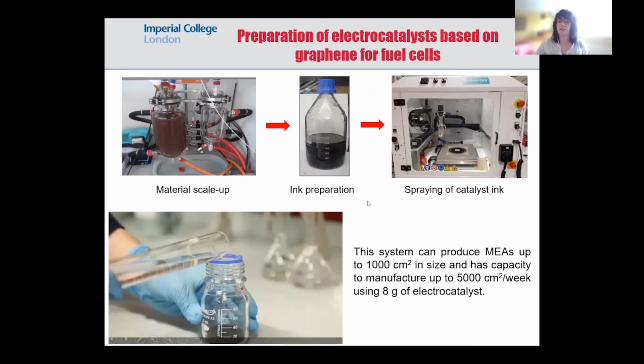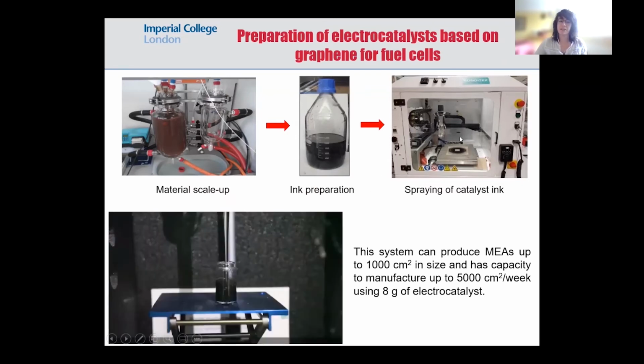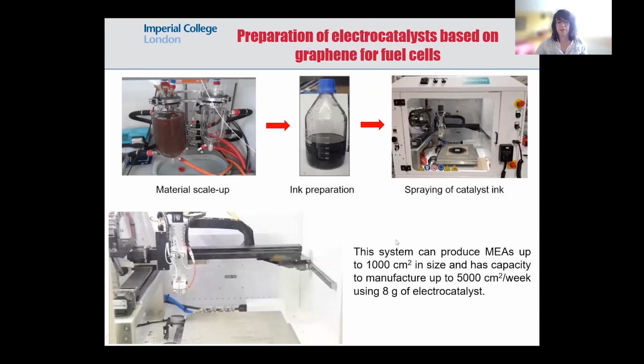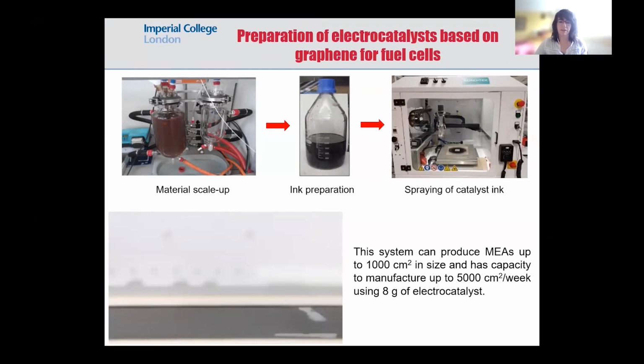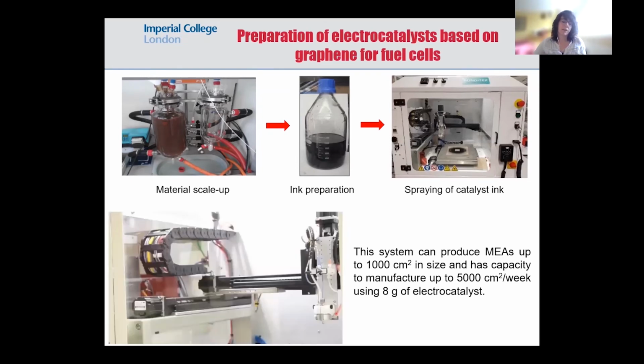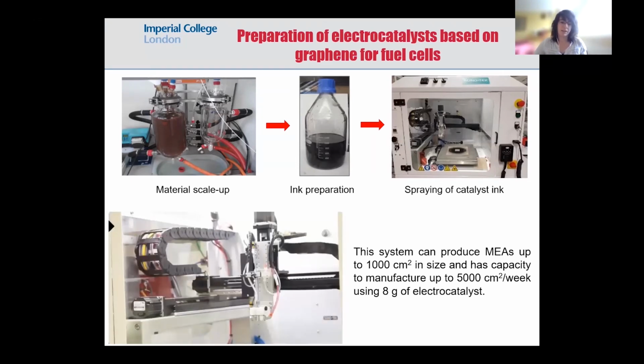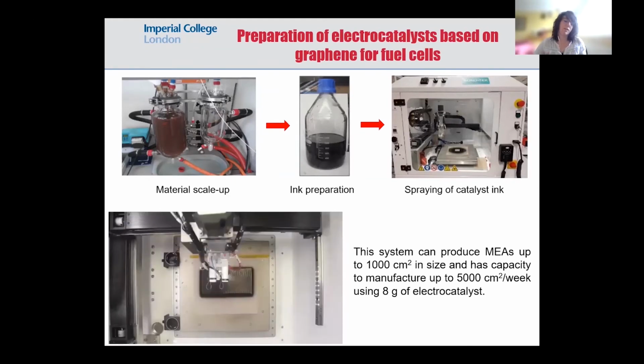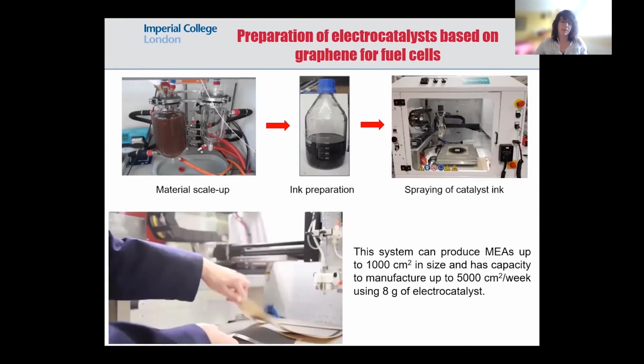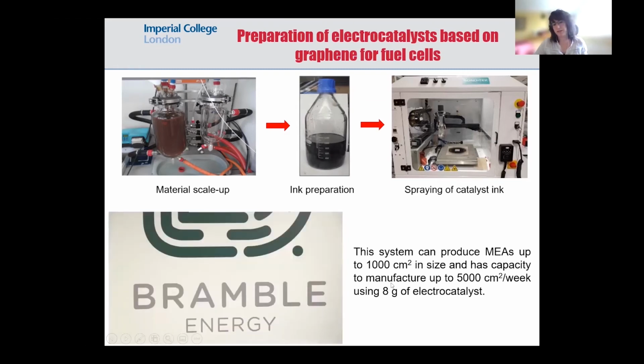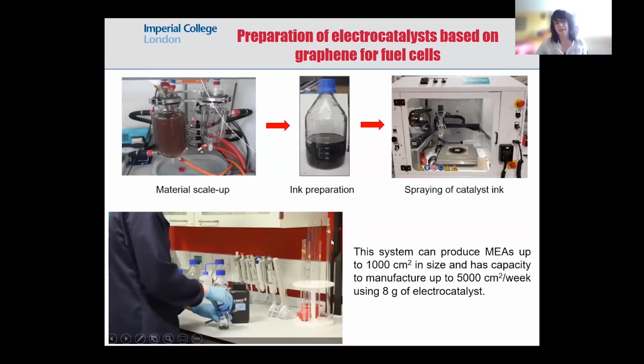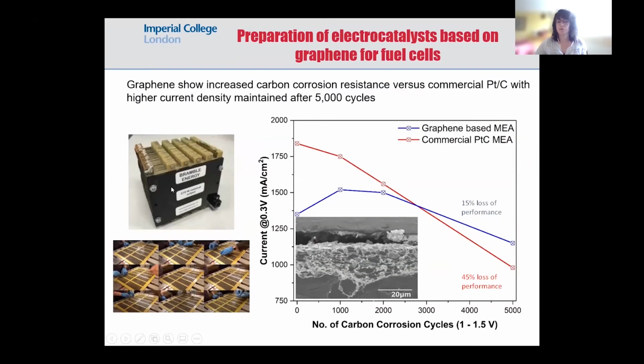That will be later sprayed using this same machine, as we can see in this video. So once we have the ink, we can produce membrane electrode assemblies in the range of 1,000 square centimeters in size, and we can scale it up to 5,000 square centimeters per week using 8 grams of electrocatalysts. So they will be the electrodes to prepare the membrane electrode assembly. So these MEAs, as we call them, can be stacked together, forming a demonstrator.